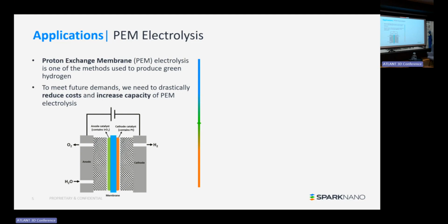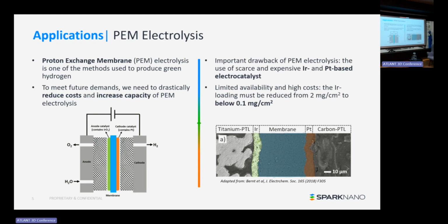In many countries, also in the European Union, there's quite an ambitious roadmap for how much hydrogen we need to produce in the coming decade. To meet these future demands, we need to drastically reduce cost and increase capacity of all electrolysis, including PEM electrolysis. An important drawback, as I already mentioned, is that it makes use of iridium and platinum-based electrocatalysts. Here you can see a cross-section of a single PEM stack. At this moment, the loading of iridium is around 2 milligrams per square centimeter, maybe a little bit less already. But this has to be reduced to below 0.1 milligrams per square centimeter to make it feasible. That's quite a big step.